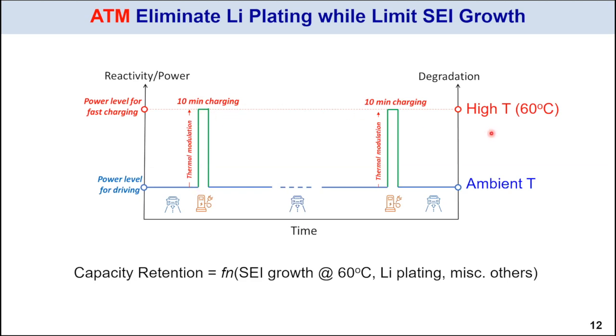And then at this elevated temperature, you get superior power level suitable for fast charging without lithium plating. You finish the 10-minute fast charging, and after that you go back to normal driving, and the cells will quickly cool down towards ambient temperature. In this case, yes, we do have accelerated degradation during the elevated temperature period, but as long as we control the time, we can limit this growth.